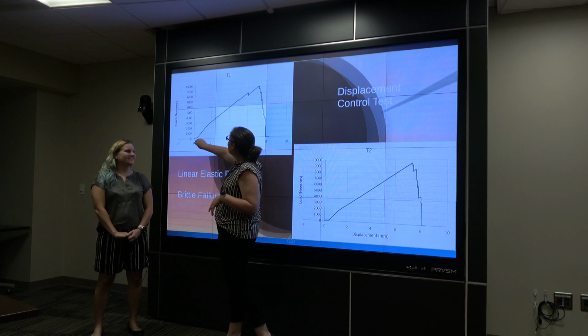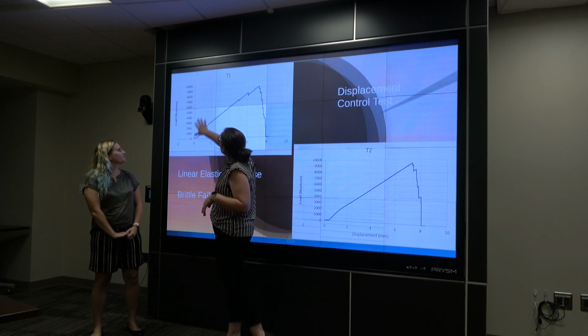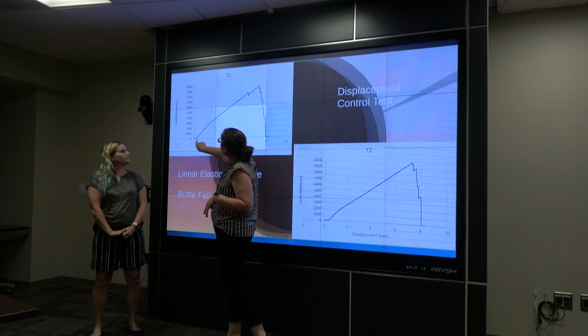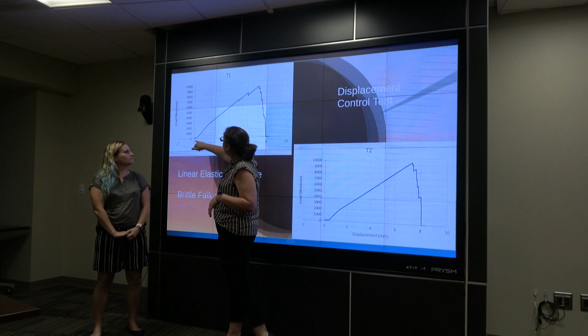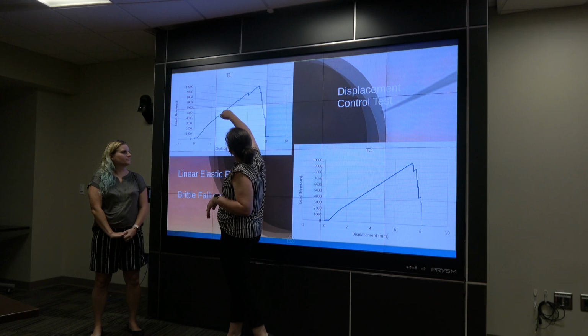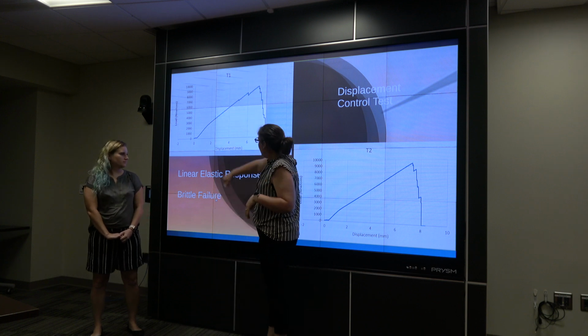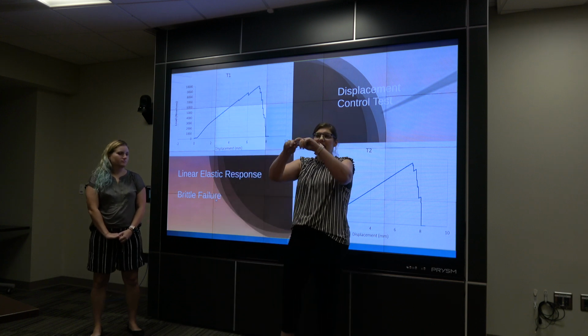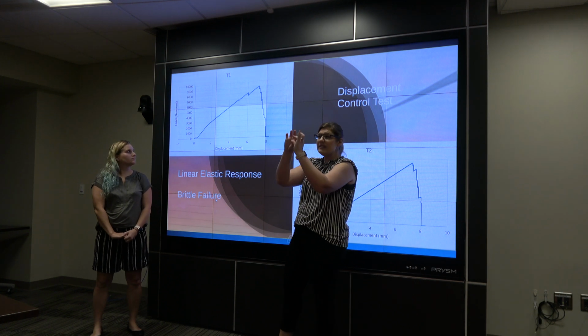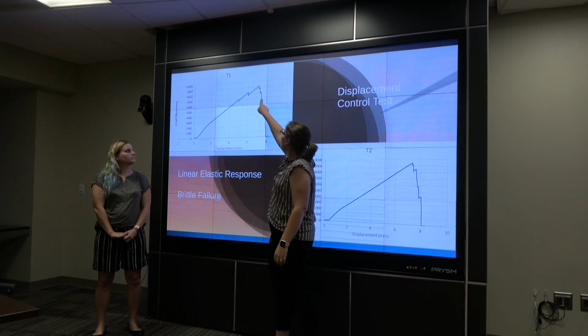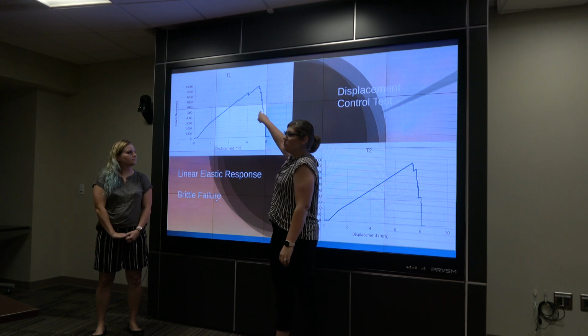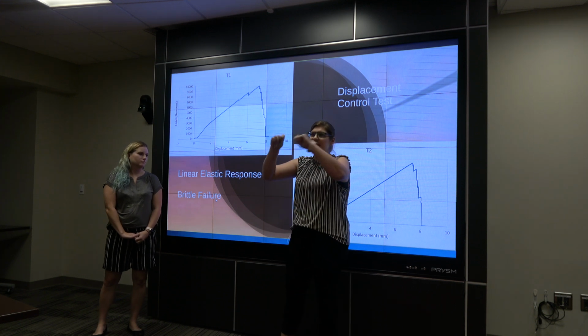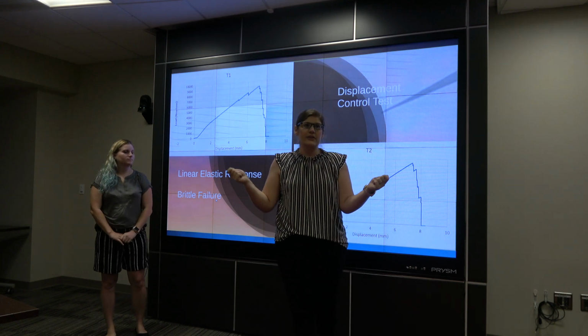Okay, so this is an example of test one. You can see as we added load to our specimen in the machine, it went up, showed a linear elastic response, and then at the end we had brittle failure. It snapped, it started that brooming, and every single one of those tensils, you can see a jump in our machine as they snapped and it went down and then had the complete failure at the very end.